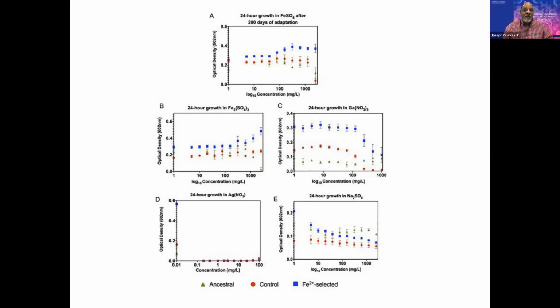When we compare them in iron 3, which is panel B, we see a similar result in which the iron 2 resistant population again shows superior growth in iron 3 compared to the controls. And the controls and ancestors are not statistically significantly different from each other.